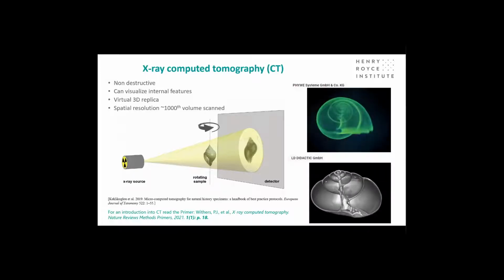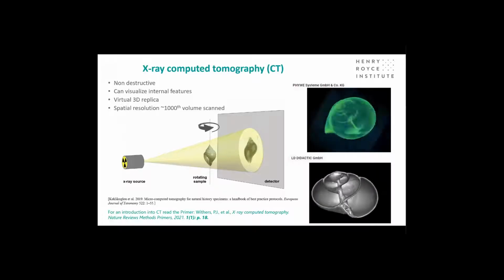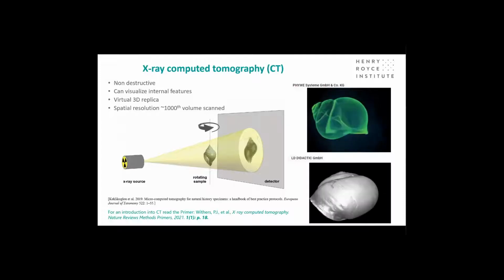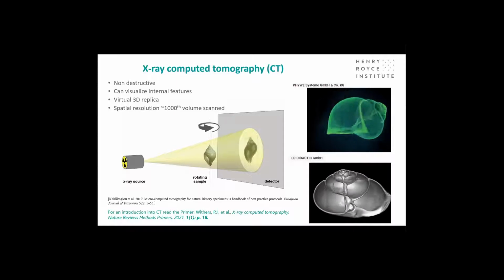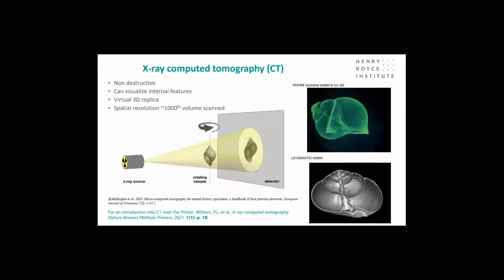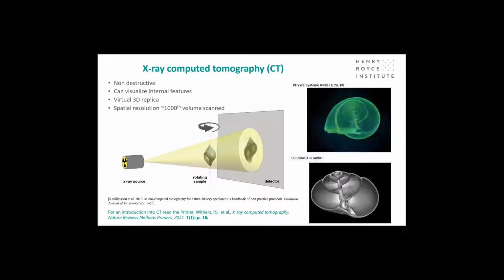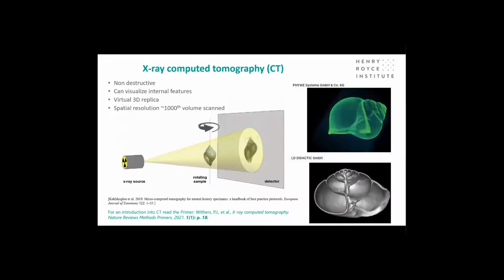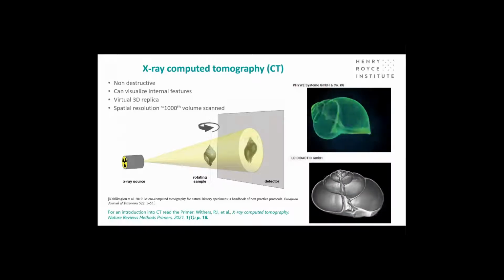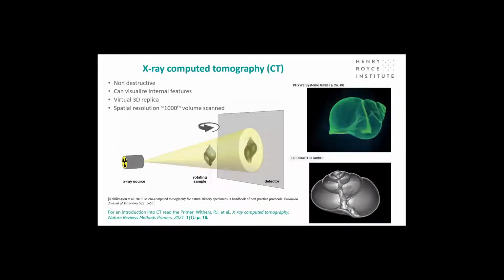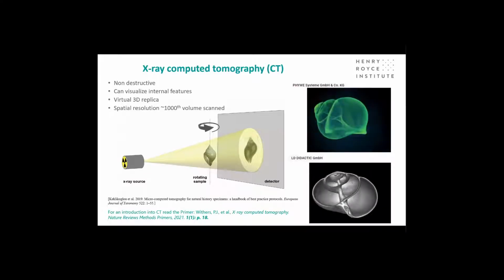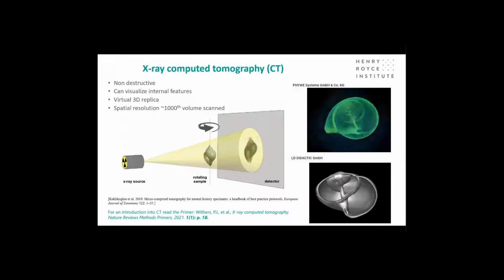There are some important issues with CT. Generally, you scan the whole sample, so the width of the sample determines the resolution. Because you normally have somewhere like 2,000 or 3,000 pixels in your image, your resolution is something like 1 to 2 pixels, or maybe 2 to 3 pixels. So your spatial resolution is generally around 1,000th of the dimension that you're scanning. If you're scanning something about 1 millimeter in size, you can get 1 micron resolution. If you're scanning something that's 10 millimeters in size, you would have 10 micron resolution. Clearly, as you move to larger and larger additively manufactured components, the resolution generally falls. There are some ways of getting around that with region of interest tomography, but it's a good benchmark to say that the resolution is about 1,000th of the dimension of the sample.